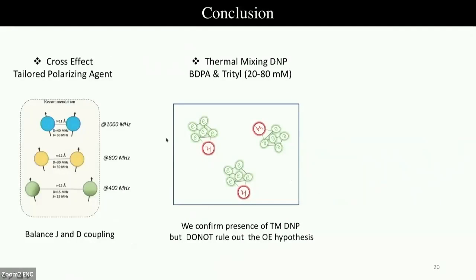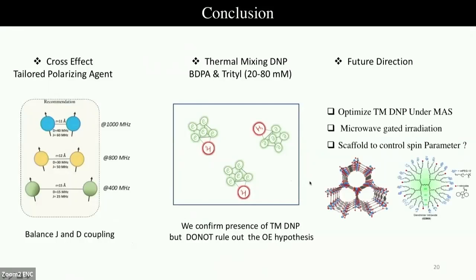I hope I showed you that in cross effects, it's possible to have high enhancement even at 1 gigahertz or larger magnetic field if we tailor the inter-electron coupling. And we have shown that it's possible to have thermal mixing DNP for clustered systems. And this seems to be the case for Trityl and for BDPA. Moving forward, I think it would be important to explore thermal mixing DNP further under MAS conditions, using controlled microwave radiation and using controlled spin parameters.